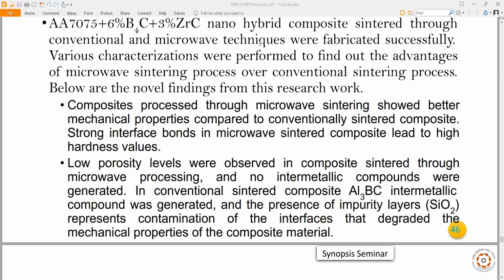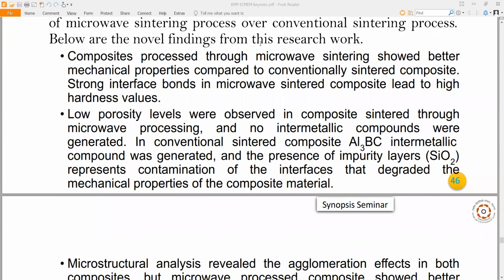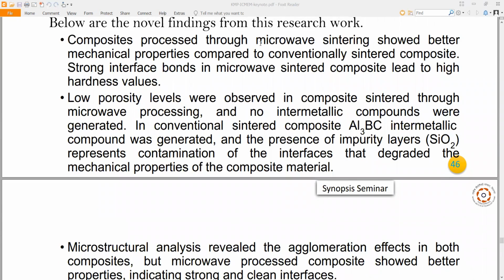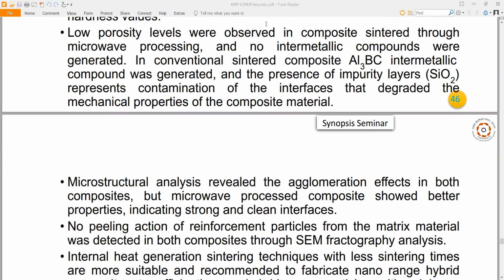Strong interface bonds in microwave sintered composite led to high hardness values, and low porosity levels were observed in composite sintered through microwave processing, and no intermetallic compounds were generated in it. In conventionally sintered composite, Al3BC intermetallic compound was generated, and the presence of impurity layers, SiO2, represents contamination of the interfaces that degraded the mechanical properties of the composite material.